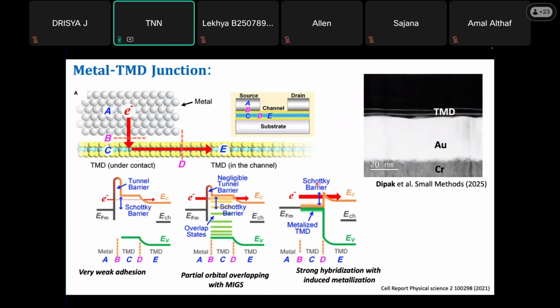Now, what you need is a very, very strong hybridization between the semiconductor and the metal, so that there won't be any energy gap between the metal and semiconductor. Then the Schottky barrier will be decided only by the phi M minus chi relation. So you need to have a good interaction between the metal and semiconductor. The real orbital interaction needs to be there, and strong hybridization with induced metallization should happen at the interface. So the physical gap should be very, very minimal. At the same time, the energies also need to interact with each other. The orbitals also need to interact so that they will have a very, very strong binding.